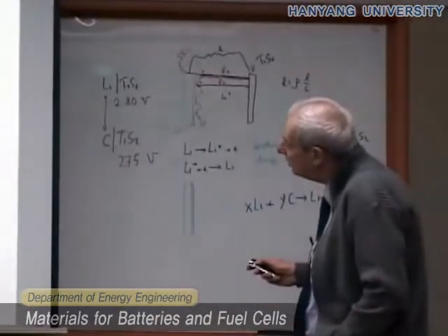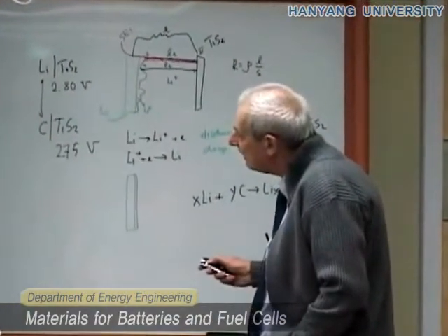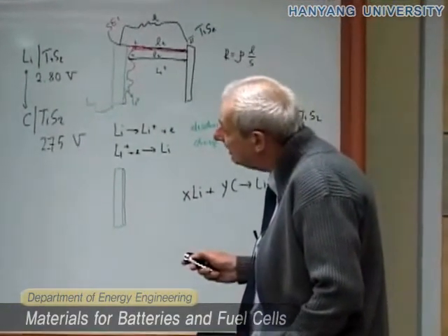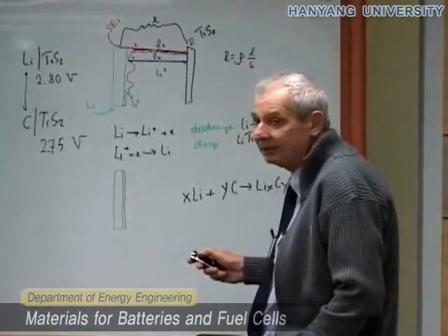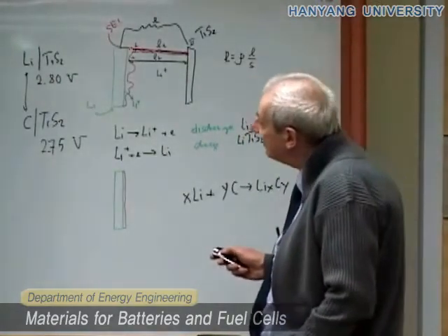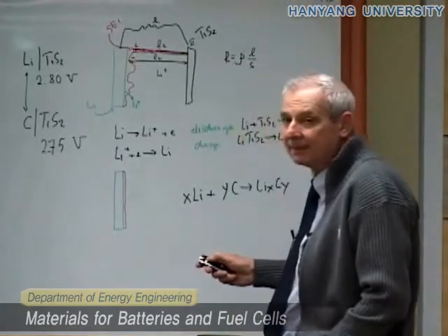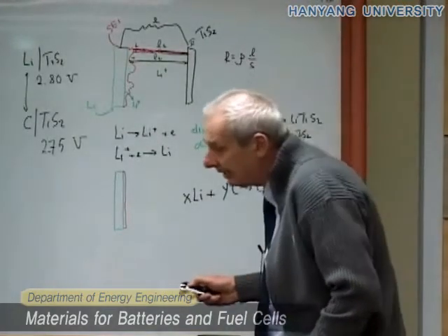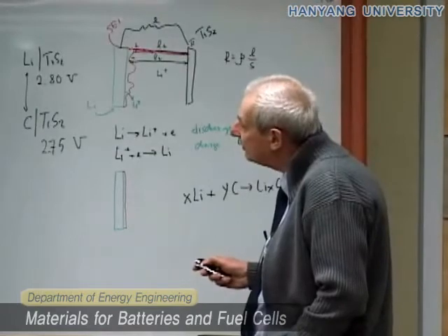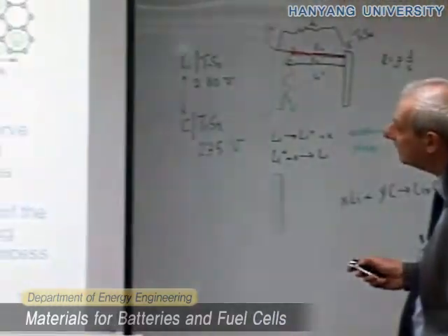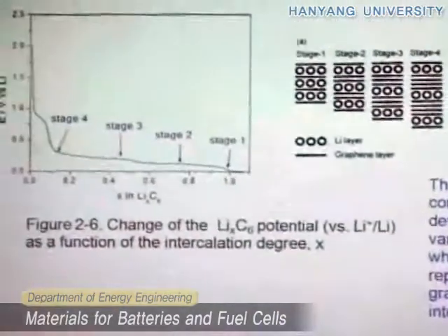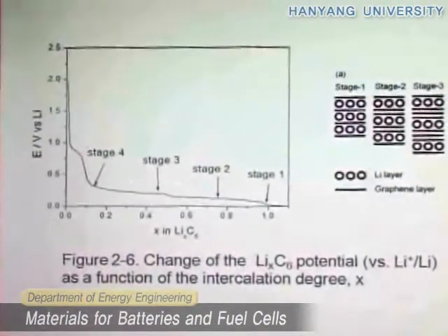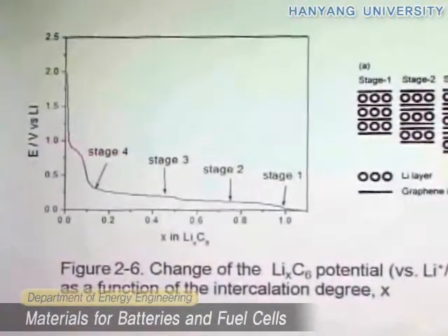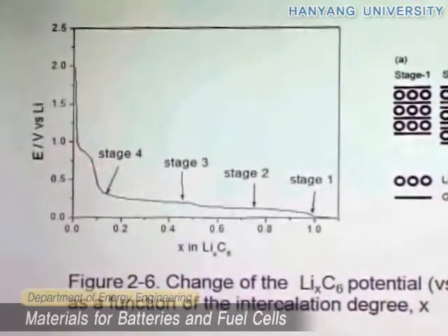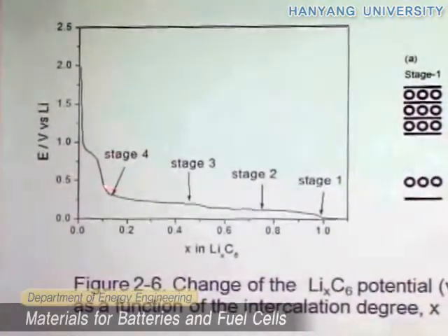Electrochemical process. And then we have a series of plateaus all the way down. Okay? So now, this one, at 0.8, is related to the decomposition of the electrolyte. This will be clear later, but as I said before, this graphite is not stable with conventional electrolytes. So we have some decomposition here with the formation of a film, as we will see, an SEI.